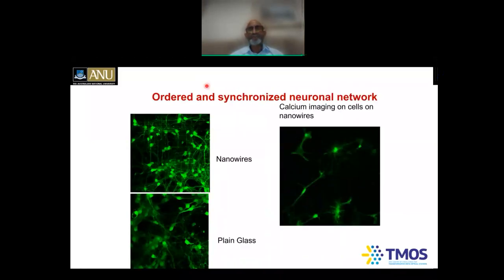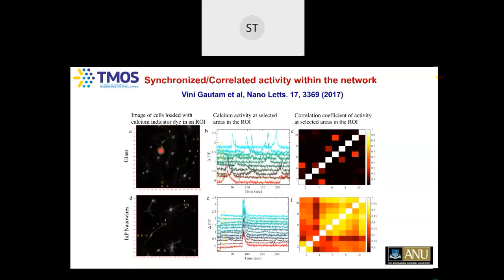What Vinnie does is that she puts some calcium dye, and as and when action potentials are fired by these neurons, ion channels are opening up and calcium ions pass through those ion channels, and then you can see the change in fluorescence as a function of time. You can take the video of this one. Then she creates correlation maps. If this neuron is firing, what's happening to this neuron, these astrocytes and all. She compares these neurons which are grown on nanowires with respect to the plain glass substrates, and tries to see the differences between them.